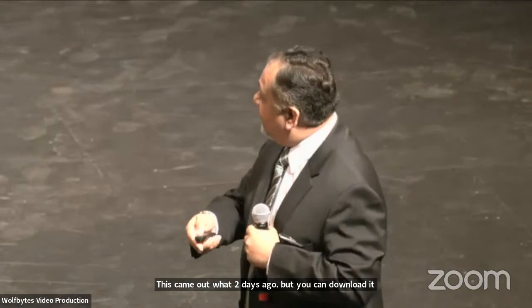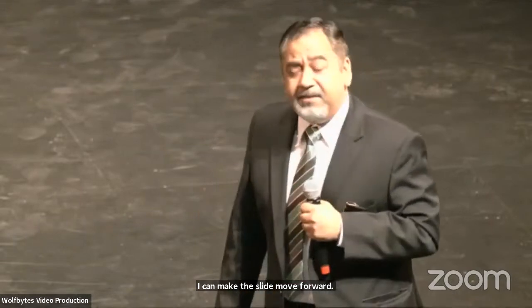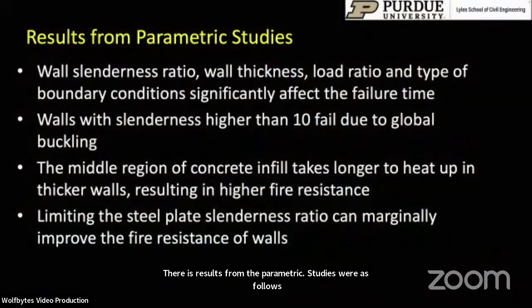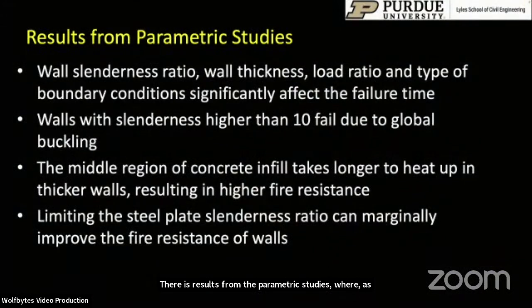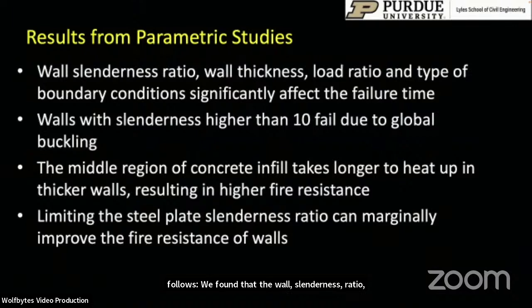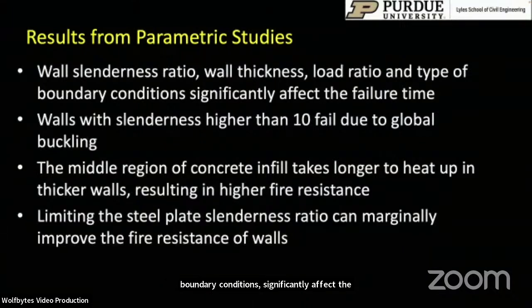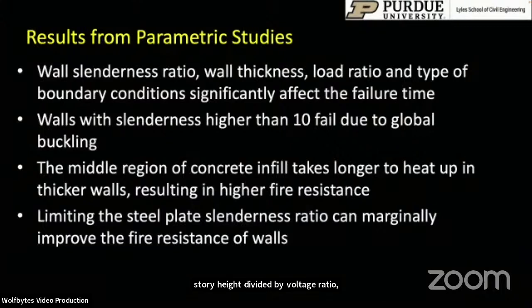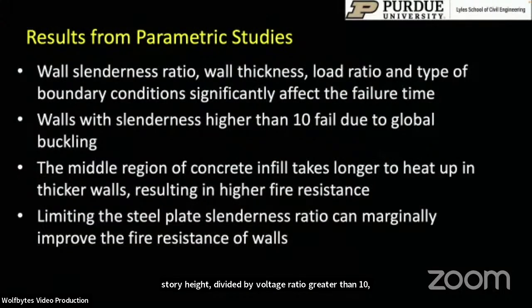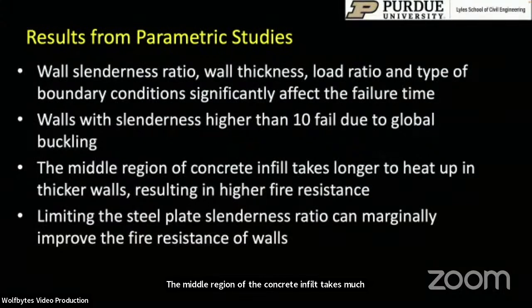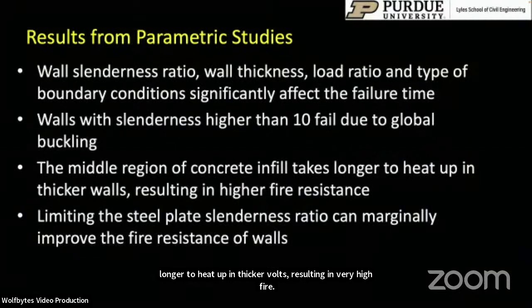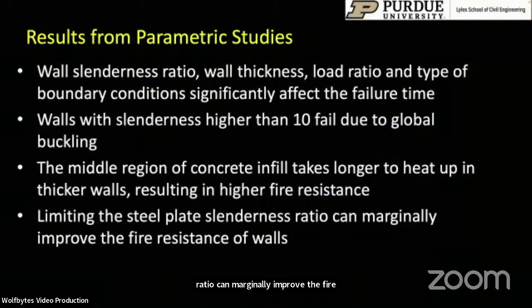I can make the slide move forward. There we go. The results from the parametric studies were as follows. We found that the wall slenderness ratio, the wall thickness, the load ratio, and the type of boundary conditions significantly affect the failure times. Walls with slenderness ratios higher than 10, which means the story height divided by wall thickness ratio greater than 10, fail due to global buckling. The middle region of the concrete infill takes much longer to heat up in thicker walls, resulting in very high fire resistance, and limiting the steel plate slenderness ratio can marginally improve the fire resistance of the walls. Next slide, please.